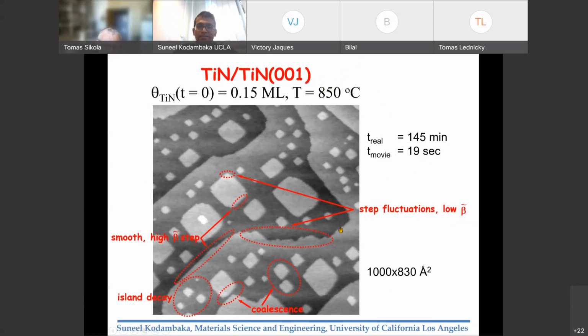And what you'll be seeing in the next slide is a scanning tunneling microscopy image and time-lapsed images obtained over a period of roughly 2.5 hours while annealing the sample at about 850 degrees Celsius. This is roughly 1/3 of the melting point of titanium nitride. And in this particular experiment, the titanium nitride islands were deposited on top of the titanium nitride surface, and the island coverage is about 0.15 monolayers.